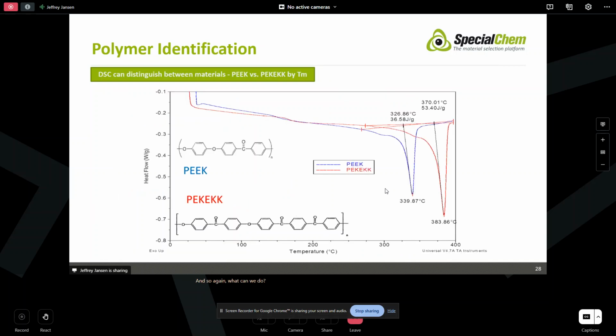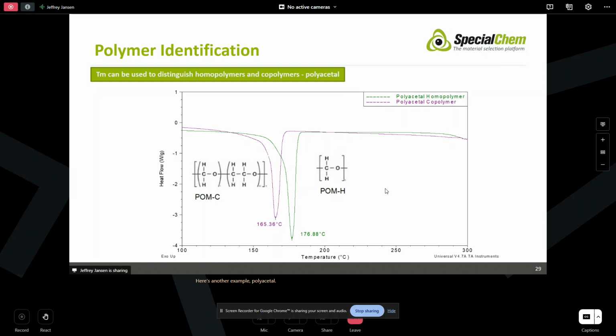And so again, what can we do with that? So here we have two more materials that are very similar. PEEK, polyether ether ketone, and then polyether ketone ether ketone ketone. Again, benzene rings, ether linkages, ketone structures, very, very similar. FTIR is going to be comparable, but they give us different melting points so we can understand what material we have. Again, very similar materials, differentiated. Here's another example, polyacetal copolymers and homopolymers. Copolymer has a very, very small amount of this ethylene functionality that is in the molecule, changes the structure a little bit, gives it some different performances. But again, those two structures are very, very similar. FTIR, our kind of first go-to technique, cannot differentiate them, but they have different melting points because of that structure. So DSC can be used.